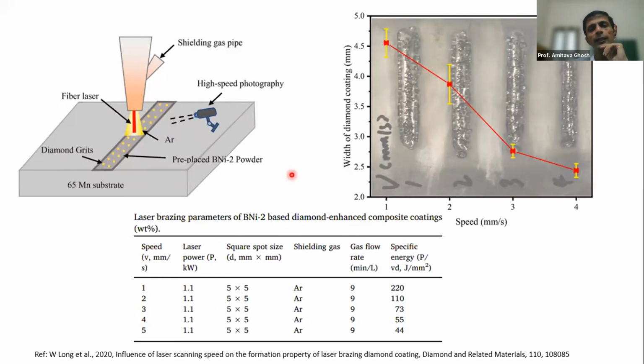One more thing I must tell: this is not being done under vacuum. This can be simply carried out under an argon atmosphere. Of course, the vacuum brazing we talked about can also be done under argon atmosphere, but that has some extra hazards, because although we use very high quality argon, the time involved in the entire process is pretty long, and here the time involved in the brazing is pretty short. That basically does not allow the diamond to degrade much chemically.